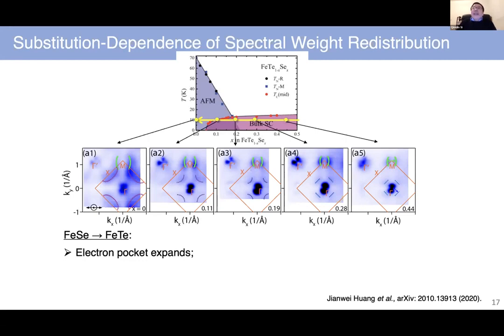In other words, you can look for hybridization and its breakdown near gamma, and experimentally that's very hard. It turns out the breakdown of hybridization is just in your eyes if you look at the right place, which is near X, where the dz square crashes down or not, depending on whether the hybridization is there or not. So there's something experimentally extremely beautiful there from the perspective of Luttinger volume, without looking at the much harder issue of counting Luttinger volume, which is very nice to do, but much harder.